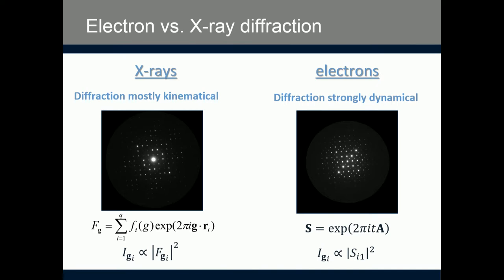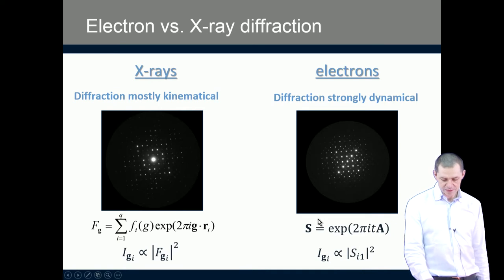This is a general expression which says that the scattering matrix is given as an exponential of a structure matrix, which contains a number of structure factors for all these reflections that are diffracting simultaneously. We take an exponential of that matrix, and the intensities are the squares of the amplitudes of elements of the matrix.